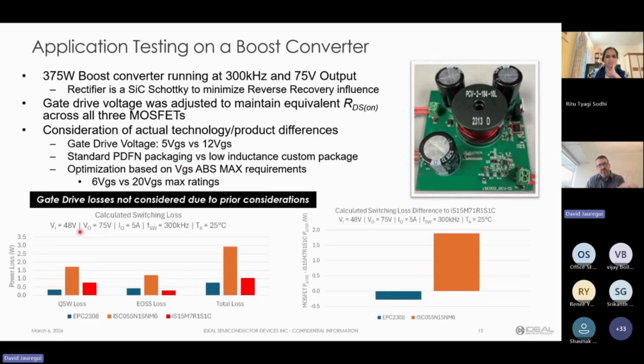these conditions, 75 volts, which is the voltage stress that the MOSFETs are going to see, 5 amps, 300 kilohertz. You start off with the I times V loss, that E on, E off, switching loss. The same three MOSFETs, the GaN in blue, Infineon in orange, and then us in red. You do the math. The EPC has, on paper at least, better switching losses mathematically than we do. And then we're in second place, and then the silicon device is obviously starting to take off.